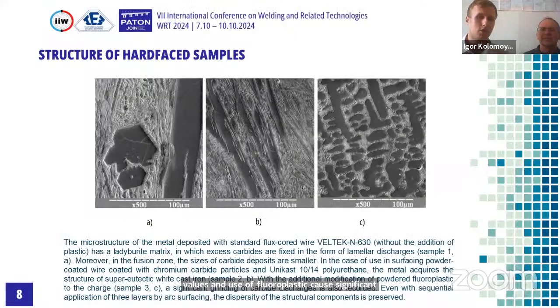Here we see the microstructure of the deposited metal. The microstructure of metal with standard flux wire Veltec N630 has a ledeburite matrix in which excess carbides are fixed in the form of lamellar discharges. Moreover, in the fusion zone, the size of carbide deposits is smaller.